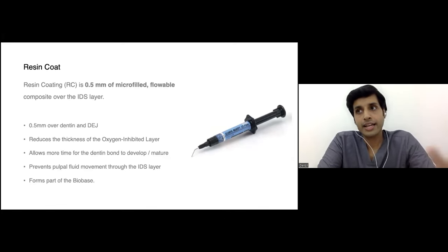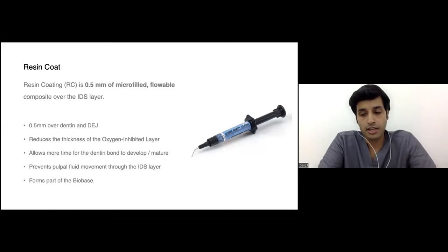It allows enough strength for that hybrid layer to resist forces that are pulling it away from dentine. It also acts as an oxygen inhibited layer for thin coats of adhesive. That's a slightly technical term, but it is something that is required. So basic composite, to sum it up, is we do an acid etching or a self etch, depending on what system you are going in for.